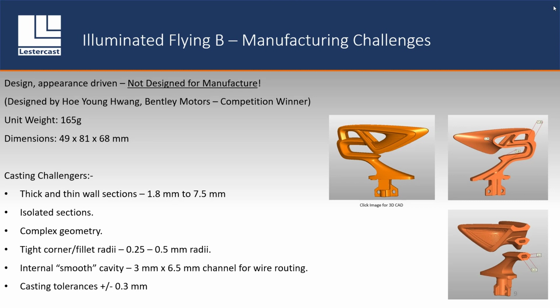And of course, an internal smooth cavity. It was okay producing a cavity to pass wires through, but we needed to ensure that those wires could be passed smoothly by the assembly team. So that was also a challenge. And typical casting tolerances plus or minus 0.3 of a millimeter on cast features, and a little bit tighter on machining.